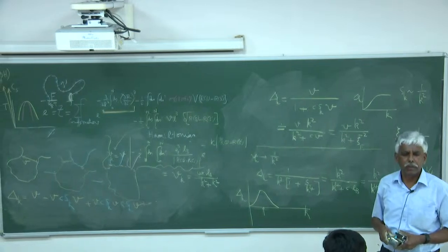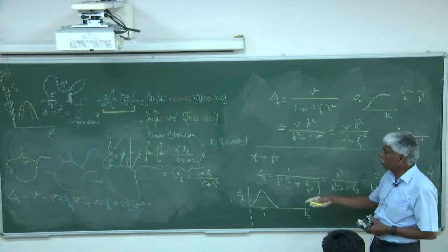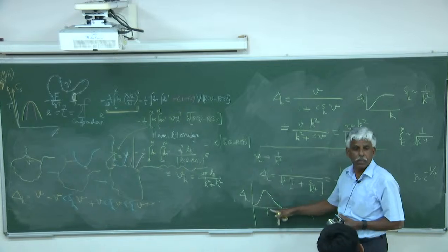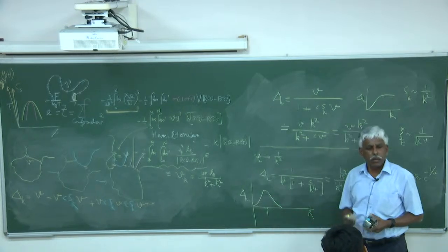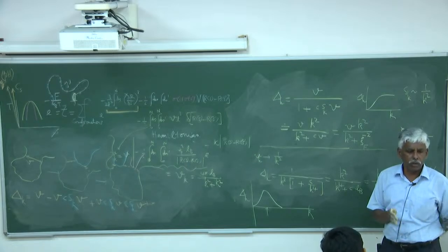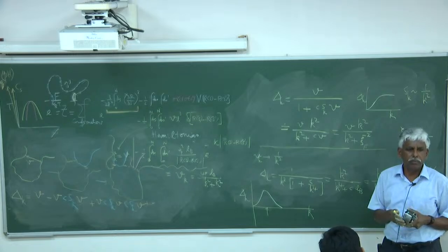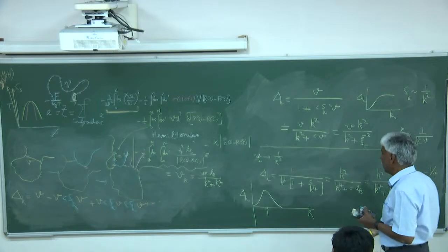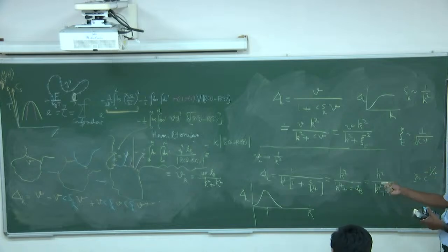You can take this and minimize it. When you minimize this, the peak position would be at 1 over c, and 1 over c depends upon this, C L B, where C is the protein concentration, LB is the Bjerrum length, and the ZP square, all those things go in here, and that's how you tune it. So some length is spontaneously preferred, because that's the free energy minimum.